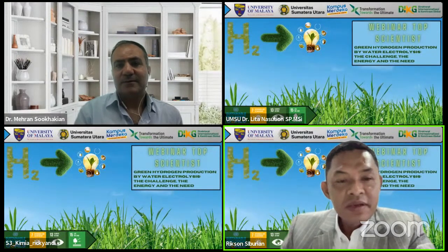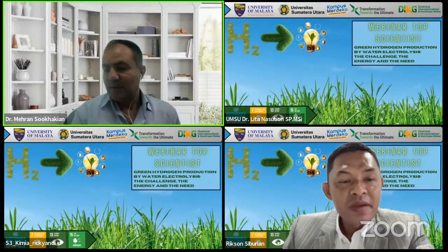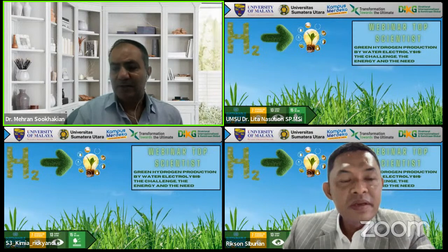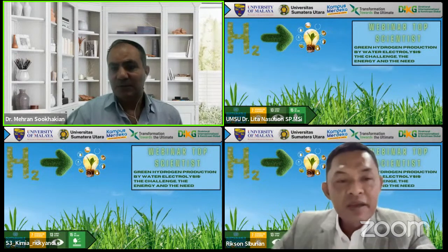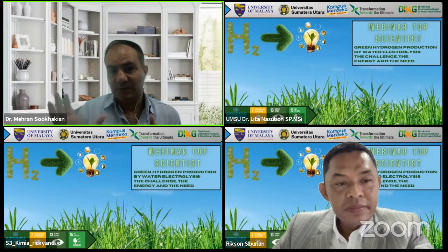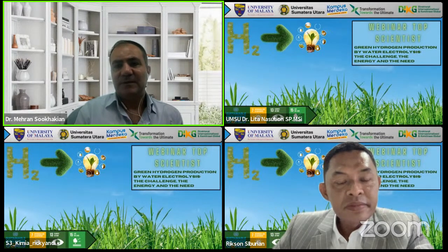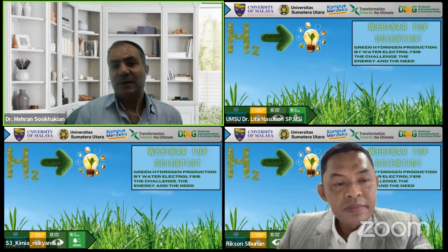And Dr. Meran, you use the precursor platina, right? You use a powder precursor of platina, right? Actually, we use chloroplatinic acid solution, H2PtCl6. Okay, so is this a powder or liquid? No, this is a liquid, the chloroplatinic acid solution. Then they disperse, for example, 10 microliters of this into molybdenum disulfide, which they synthesize using hydrothermal. After that, at a temperature around 70 or 80 degrees, they use the chloroplatinic acid solution with some reducing agent, like hydrazine, mixing this platinum precursor in the presence of the reducing agent for 24 hours, just simple mixing. Okay, I see.